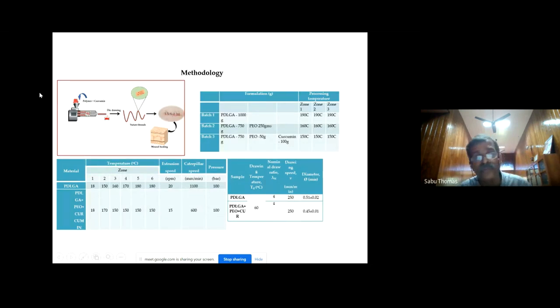we made use of a biocompatible polymer, which is nothing but a copolymer of PLA and glycolic acid. We introduced curcumin, and we went for an extrusion process with controlled conditions, and then we went for a solid state drawing process to draw the fiber so the diameter could be decreased. And we made different types of combinations. You can see this is PLA glycolic acid, neat. PLA glycolic acid with the PEO. PEO will act as a plasticizer. PDLGA and PEO plus curcumin. Look at, we have made three different combinations. And we made an extrusion process followed by solid state drawing. And utilized as a surgical suture for closing your wound.